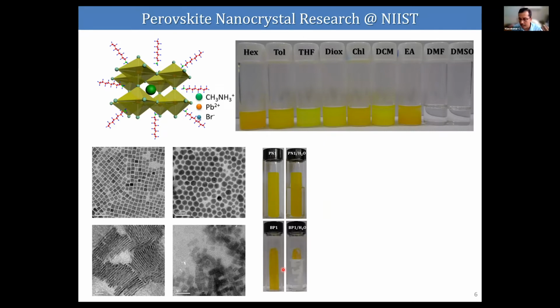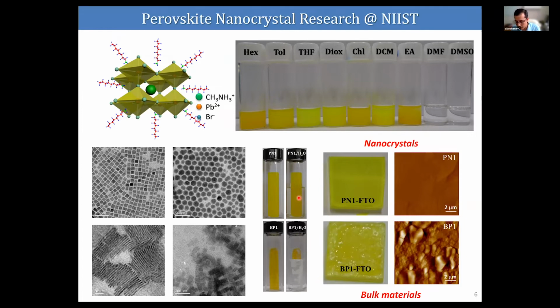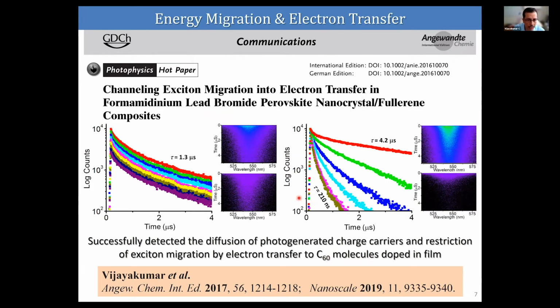The 3D perovskite can decompose within a few seconds, but our material can survive for several hours. And the film quality is very, very good, which is important for device applications. And we did extensive studies of how these materials behave when we excite them, and what the properties are, like excitation energy migration in these materials, and electron transfer from this material to suitable acceptors like fullerenes. And we realized that these materials in the film state can show very efficient diffusion of charge carriers.